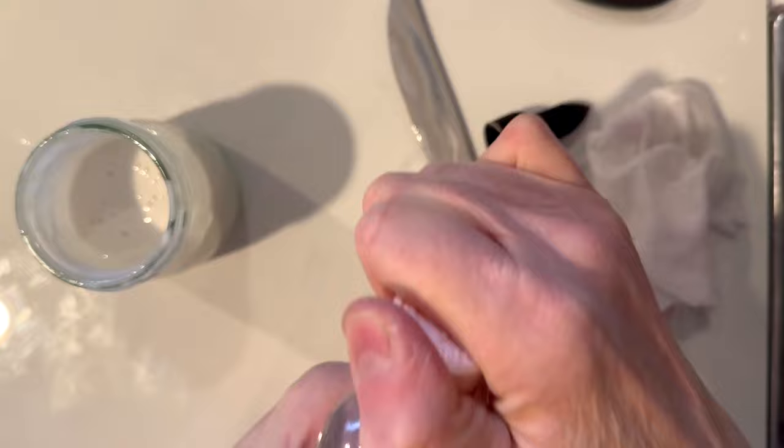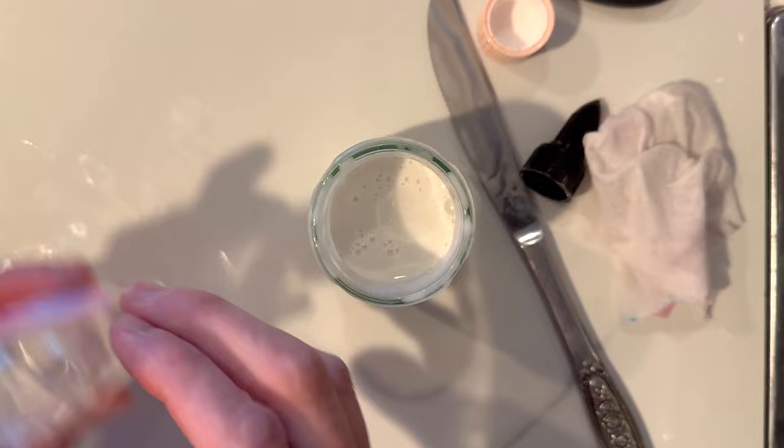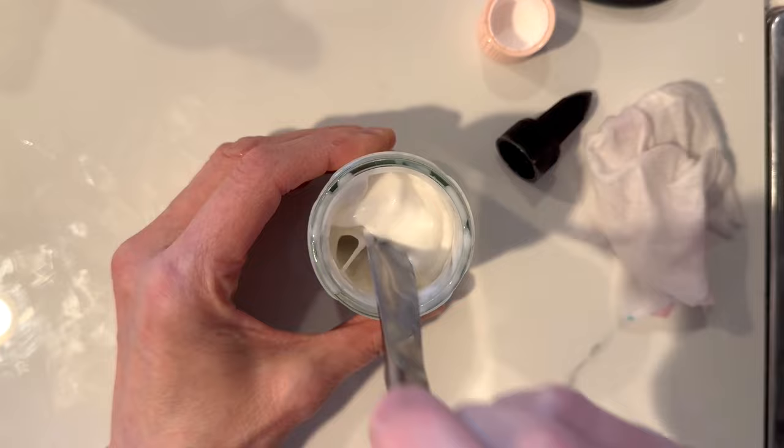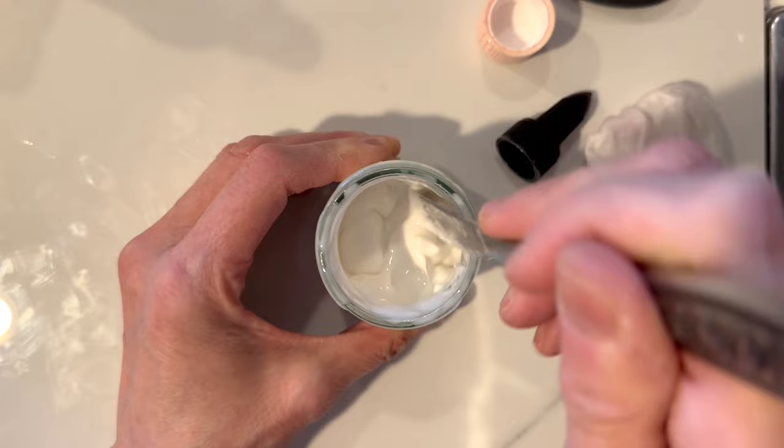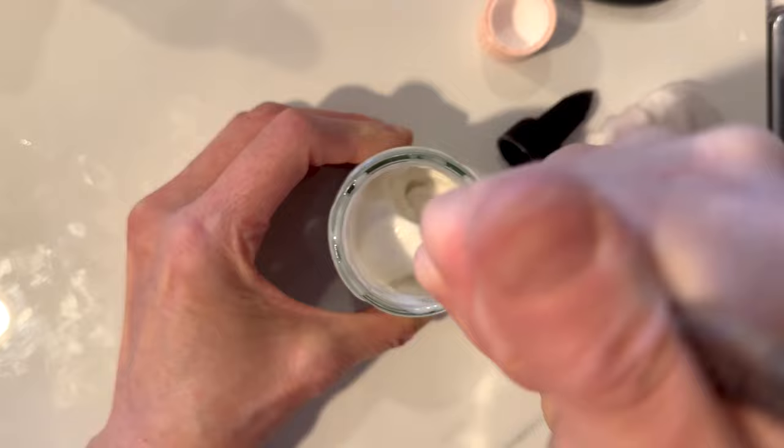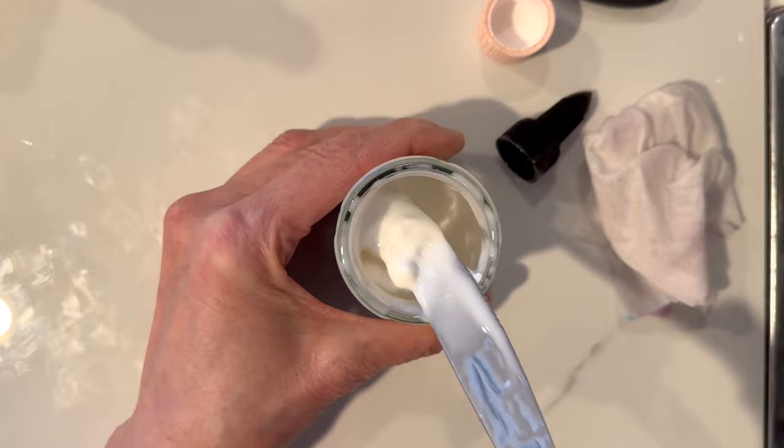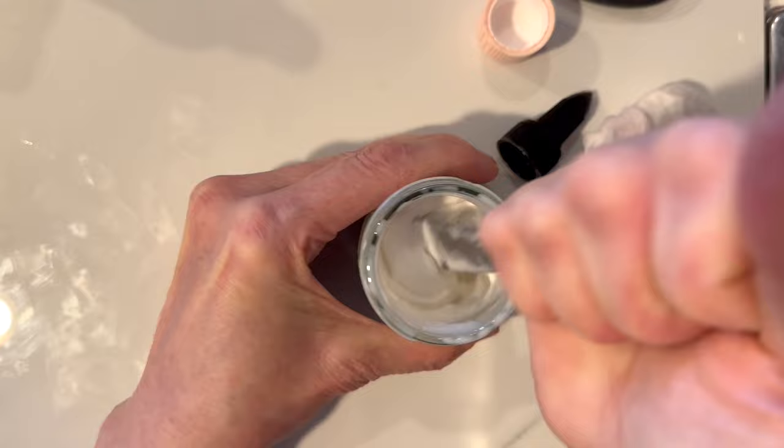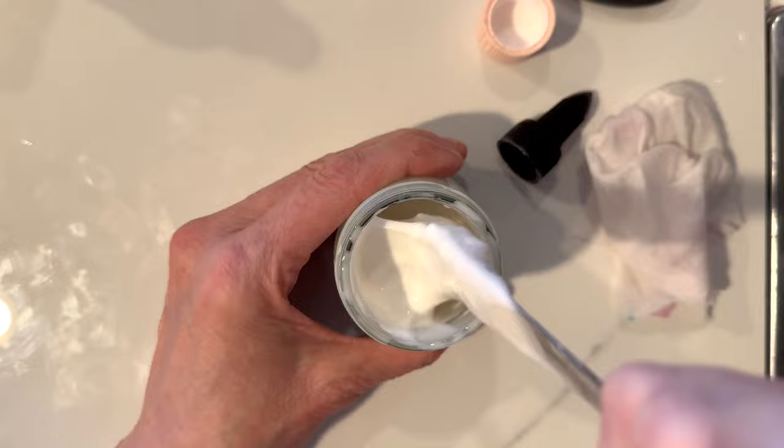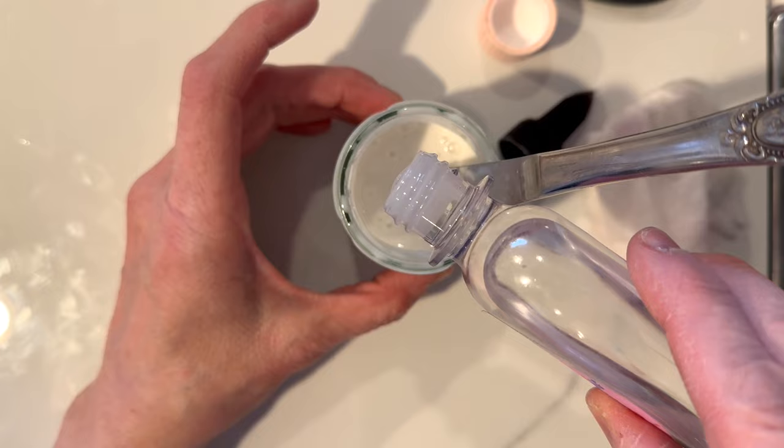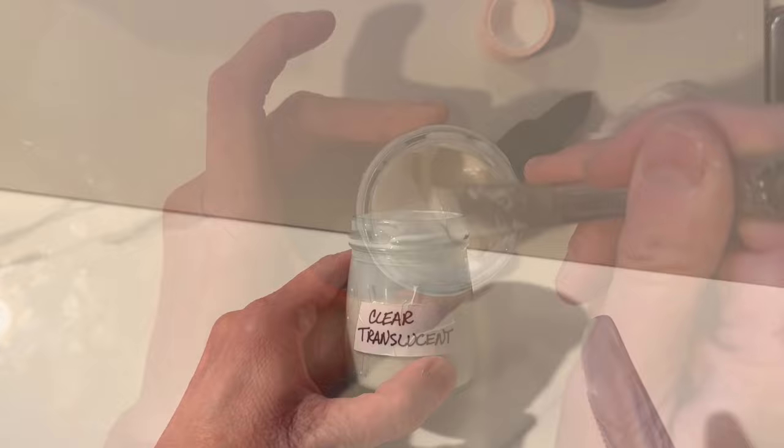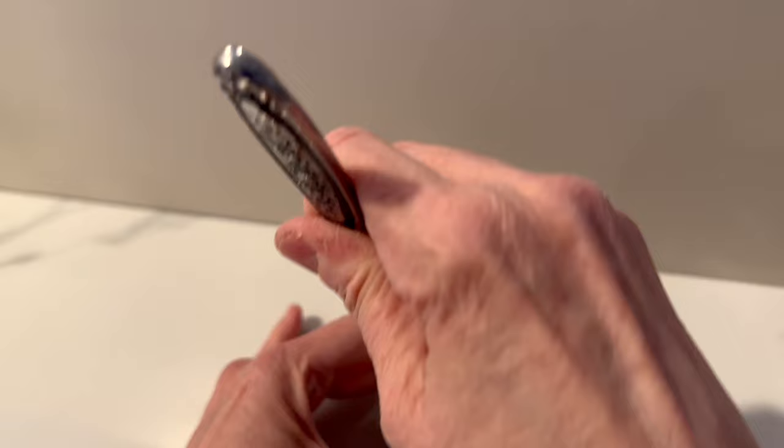So I'm going to use a help here. This is my baby oil, and I love this. Now I know there are some polymer clay artists that say do not use this stuff. I'm sorry, I don't see how it's not a help. It has been very useful in this context, especially when I'm trying to do the transfer technique, because I want to get this into a running, very much a running liquid. To get it there, sometimes it needs a little help to get itself back to where it's reconstituted into working order. So I start with like six to seven drops, especially if it's really hard, or even more just to get it working. And then once you have it really working, then I ebb off. So don't use a half a bottle, use a little bit at a time. But you can tell right here now I've gotten it into a very nice runny form, and that's what you're looking for.